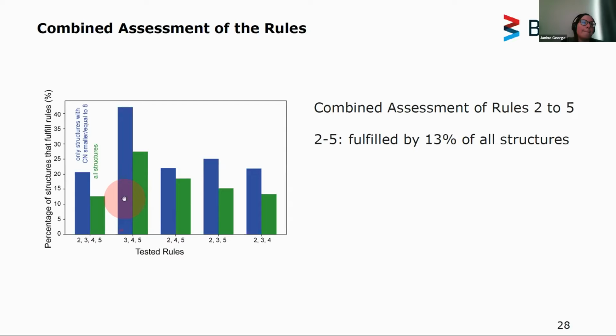And then we found that only 13% of all structures fulfill these rules 2 to 5. If we go to only structures with coordination numbers smaller than 8, we are at 20%. It's much, much better. In the case of the third rule, it helped very much to reduce these kind of coordination numbers, but for the overall assessment, it didn't.